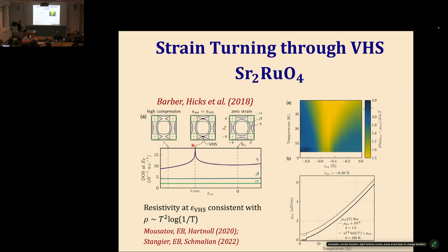Okay, so a few lessons here. Strange metal behavior doesn't have to have a strange origin. Nothing but a Van Hove singularity. The presence of this high density of states that gives rise to the strange metal can also make the system unstable to another kind of order. In this example, superconductivity, which is very strongly enhanced close to this point. I like this example. I think this is one of the examples where we actually can understand.